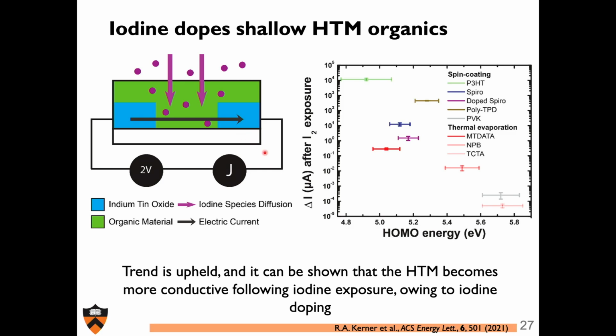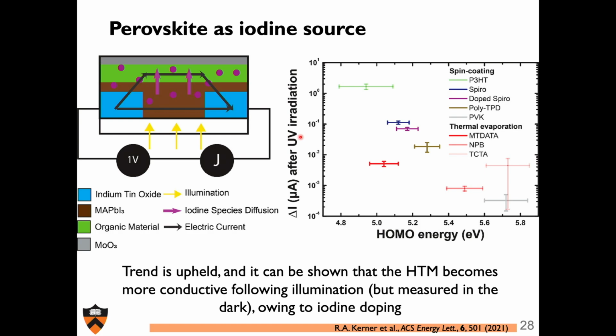To close this picture, we can see that iodine also dopes these shallow hole transport layer organics. The delta I, the change in current upon exposure, is huge the shallower the HOMO I have, because I'm effectively doping it better, and therefore the conductivity goes up. To finally close that loop using perovskite as the iodine source, I have this stack here, and what I'm checking is the conductivity of the organic bridge. We can see the same trend.